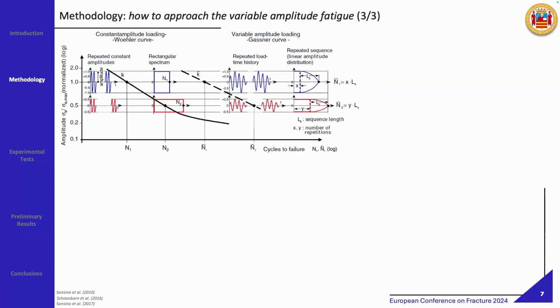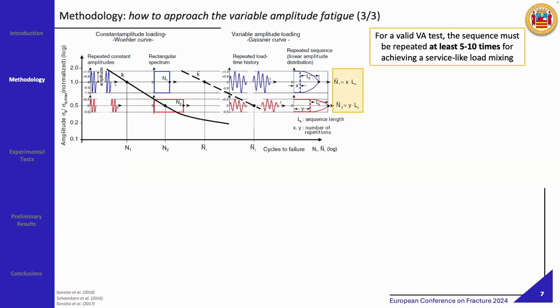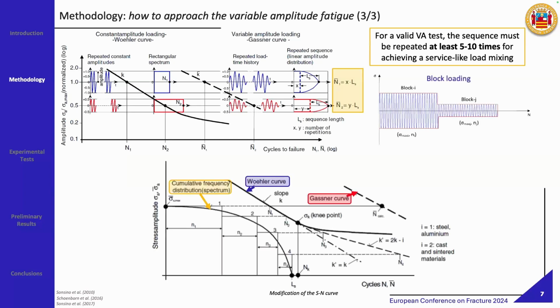While if we have variable amplitude loadings, by applying the same sequence many times, in general, according to literature, from 5 to 10 times for achieving a service life load mixing, we can then obtain the fatigue life curve, which is the Gassner curve. So if we consider a general block loading characterized by blocks of different amplitude and duration, from the cumulative distribution, for each block, entering the Wöhler curve, we can obtain the number of cycles to failure, and then we can compute the Gassner curve. As often carrying out experiments with variable amplitude loadings is demanding, time consuming, in general is difficult, so the Gassner curve can even be computed.